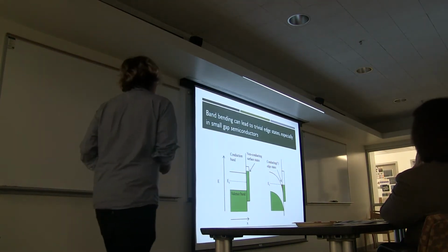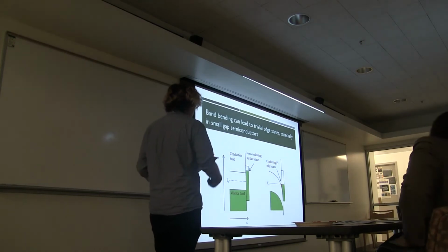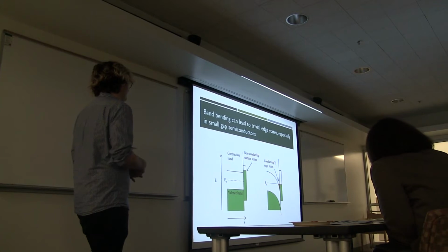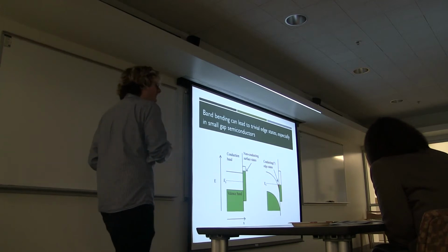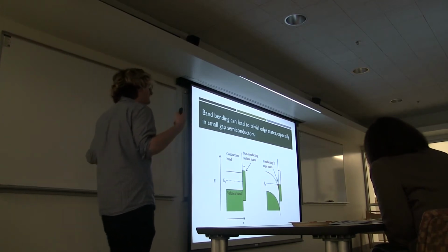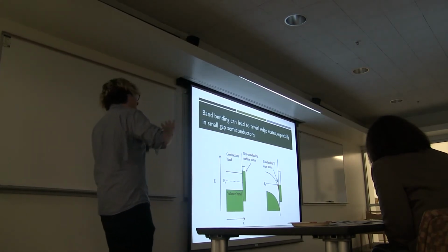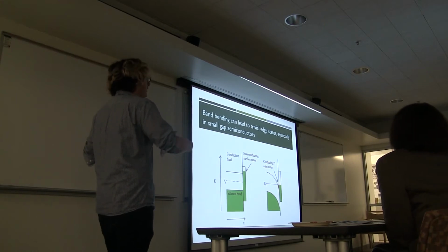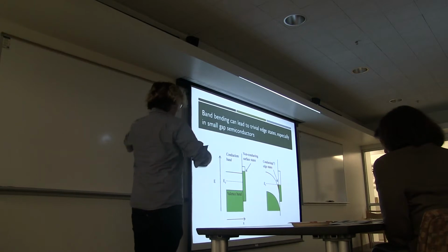Yeah, so I'm a little bit behind, so I won't go into this fully, but one possible origin of trivial edge states is something called band bending. And the point I'd just like to make here is that the band gap in these materials is extremely small, orders of magnitude smaller than the normal scale of band bending in indium arsenide. Although those values are taken in a different configuration, it's not too hard to imagine a situation in which the band bending bends farther than the gap.